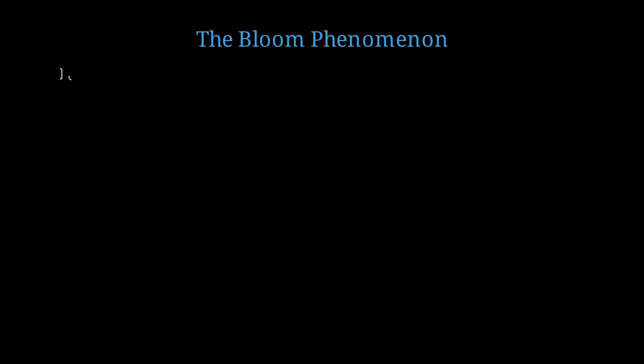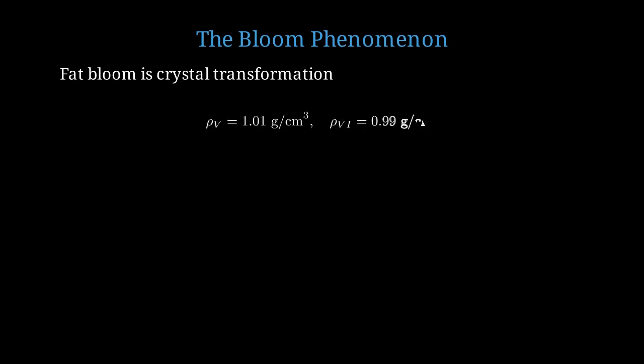What causes this? Fat bloom occurs when unstable crystal forms slowly transform into Form 6. Form 6 has a different density and crystal structure, causing fat to migrate to the surface. Form 5 has a density of about 1.01 grams per cc, while Form 6 is about 0.99 grams per cc. This 2% difference causes volume expansion and surface irregularities.